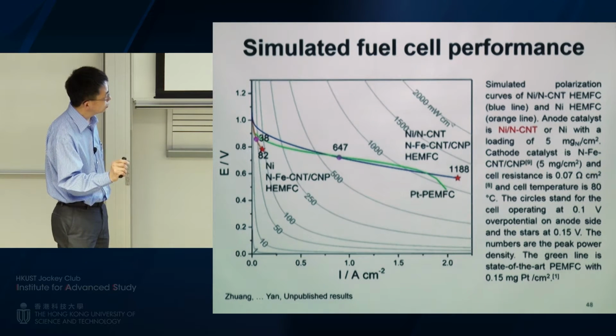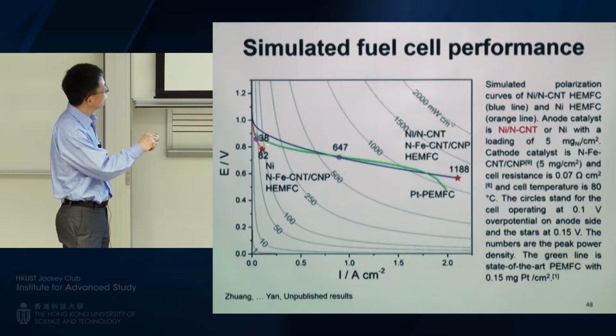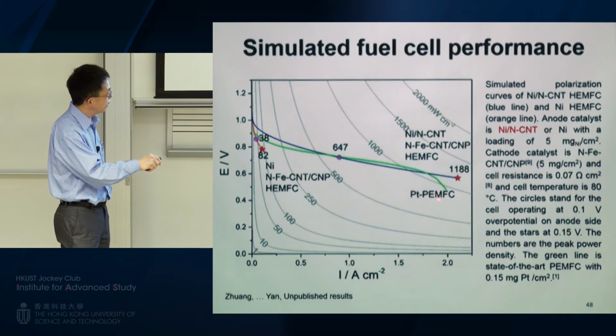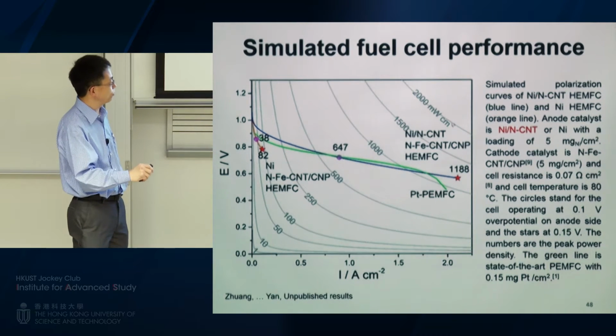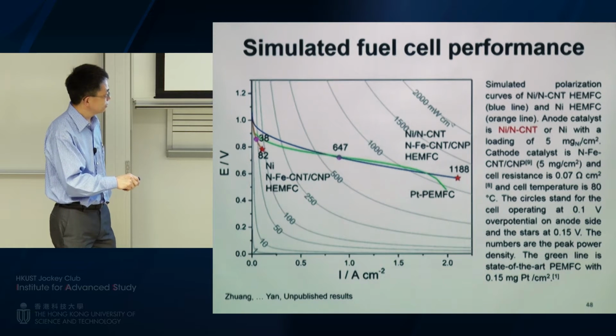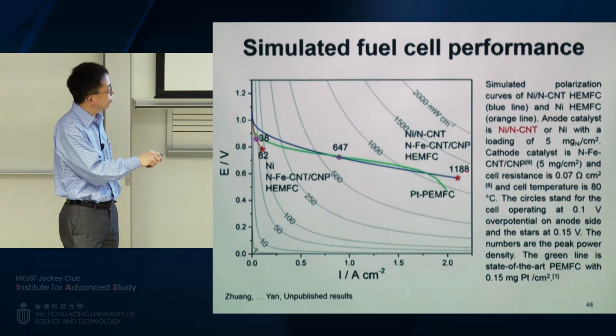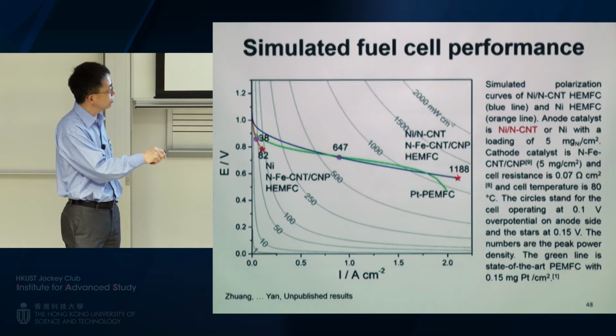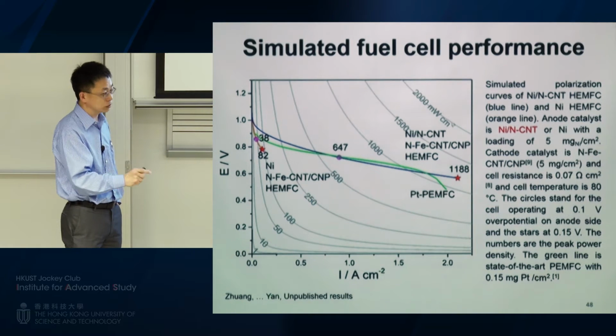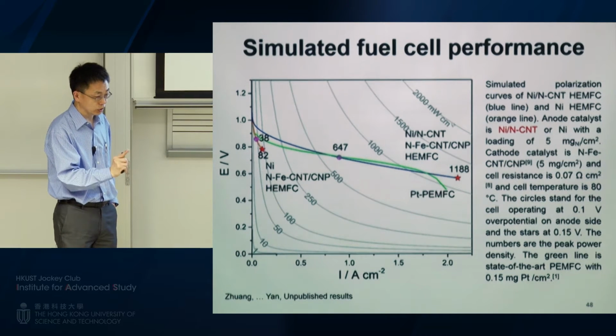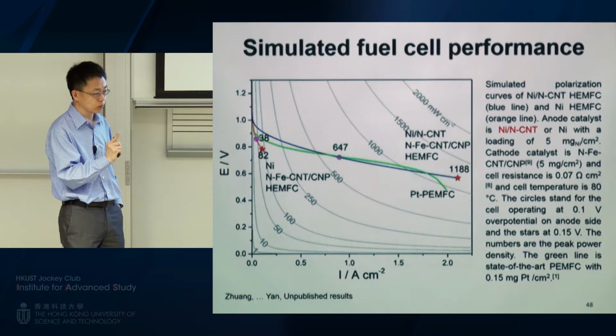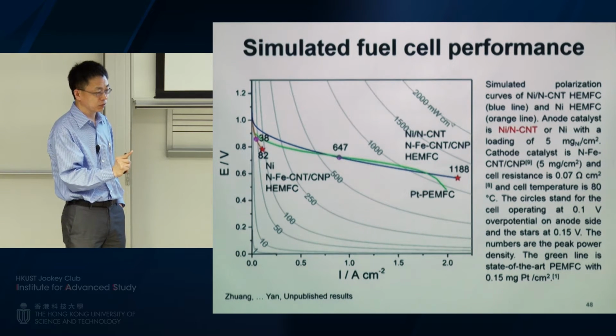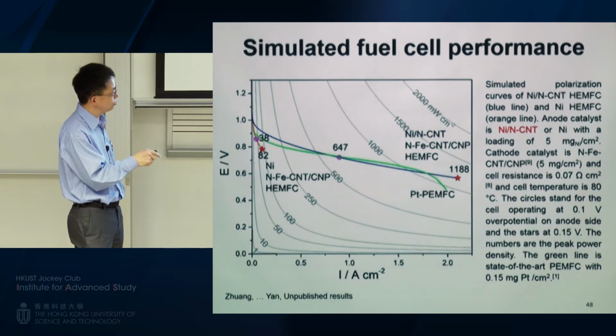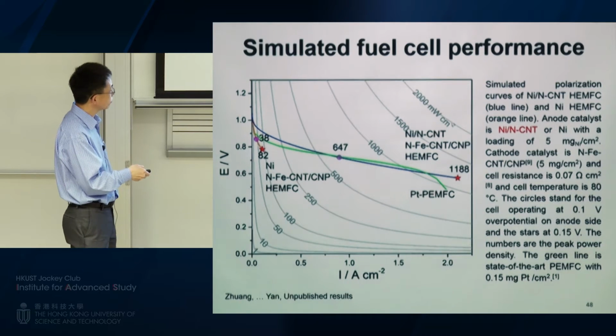I think I should correct myself. The green curve is the PEM fuel cell. The blue curve is our own curve. You can see that this is very, very exciting to us. What this tells us is we really need to get our nickel catalyst more stable. We don't need to make the nickel catalyst more active anymore. If we could, certainly we'll benefit. But really what we need is just make it more stable.